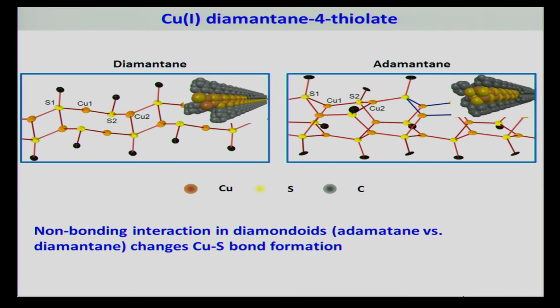And what happens here is the only thing that has been changed is that we're changing from adamantane to diamantane, and by varying the size of the diamondoid, we're changing the interaction between these diamondoid species. And as you can see here, this change is so significant, the interaction is so strong that it starts to modify how the bonding formation between the copper and sulfur atoms in the core behaves. So this is something that I don't think anybody else has been able to observe before in the growth of this one-dimensional, or in general in material synthesis.